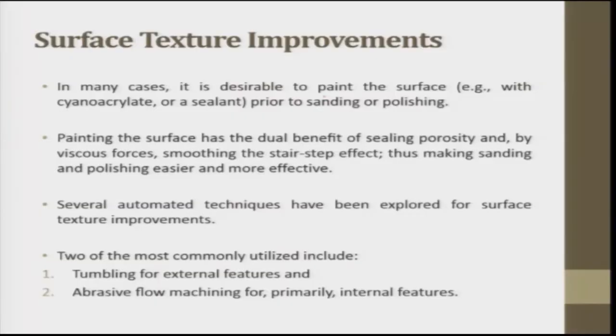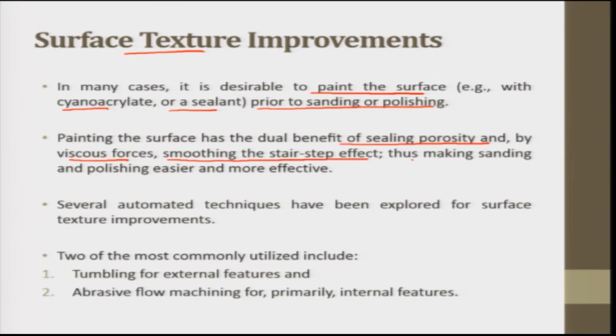In many cases it is desirable to paint the surface to improve surface texture — for example, with cyanoacrylate or a sealant — prior to sanding or polishing. Painting the surface has the dual benefit of sealing porosity by viscous forces, smoothing the stair step effect, and thus making sanding and polishing easier and more effective.